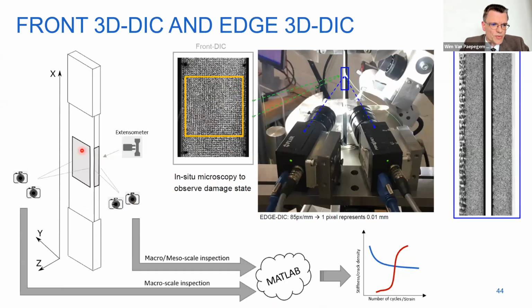So if you first look to the left to the schematic figure here, we already have the speckle pattern on the front surface where we look at with 2 cameras. And now we add a speckle pattern at the edge. And we also look with 2 cameras to it. And we have an extensometer, which is just a validation for the strain measurement in axial direction. We always do that as just a backup. All these measurements are synchronized with force, displacement, thermocouples, and so on. And here you see what we see with the cameras. So this is the frontal DIC pattern, which is basically the green arrows here, which you do not see here from the edge. And these are the edge patterns that the 2 cameras from the side see.